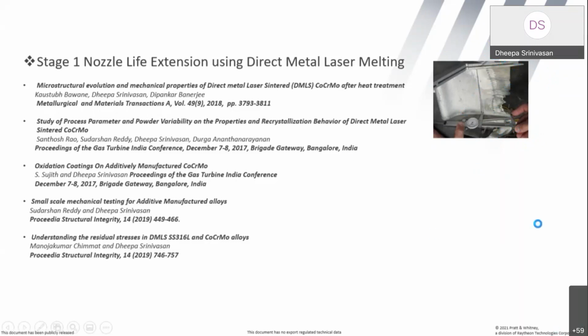You can see this like a moth-eaten leaf, and it has got severely damaged, and all these vanes were discarded. So what we did is we came up with a solution 6 years ago, as that time additive was not such a big buzzword, but we were a little ahead of time, I would say, for this particular series of experiments and qualifications that have been done for the gas turbine hot section components, wherein we proposed, let us do two things. One is, let us cut off the damaged part and let us make an additive laser powder bed fusion insert or coupon, and let us join them by welding or pressing.